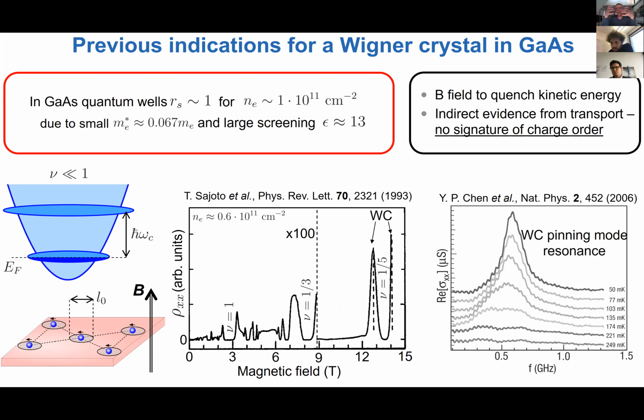it's an insulating state. But by applying radiation or modulation at the pinning frequency, one should be able to induce conductivity, and the fact that this picks up at low temperatures is an indication that this could be a Wigner crystal, pinned Wigner crystal state. Now, there's a relatively long list of work going back 30 years, as